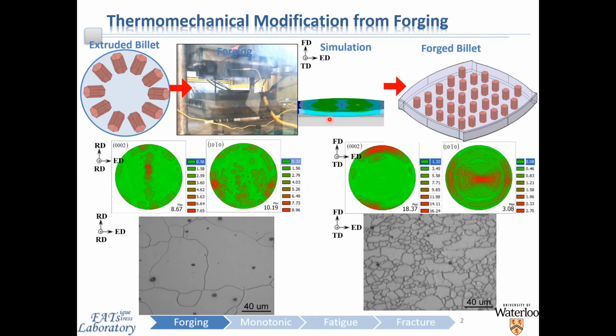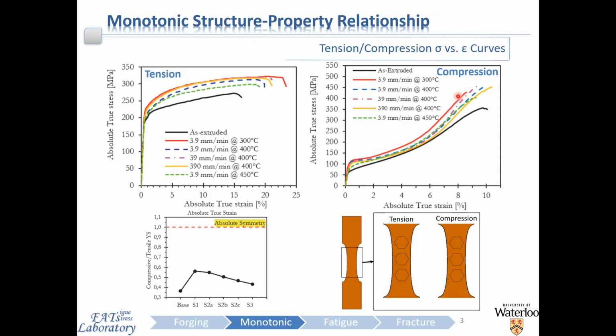The obtained microstructural analysis showed that the extruded AZ31B magnesium alloy possesses a bimodal grain structure with strong basal texture. In contrast, once forged, the material reoriented its grains and had a refined grain structure with a modified texture, such that the C-axis reoriented itself to be coincident with the direction of forging, as can be seen here. You can also see that the initial crystallographic texture, which is axisymmetric, illustrated by this schematic, then evolves to this planar basal texture as shown here.